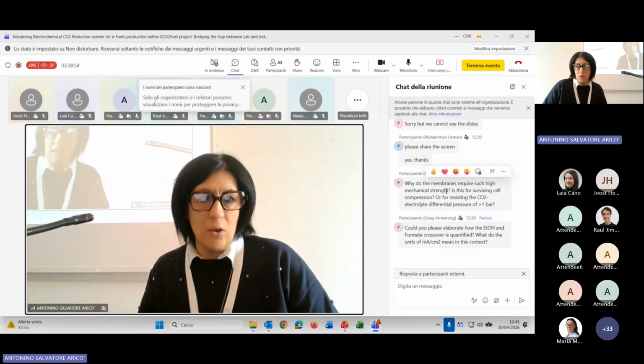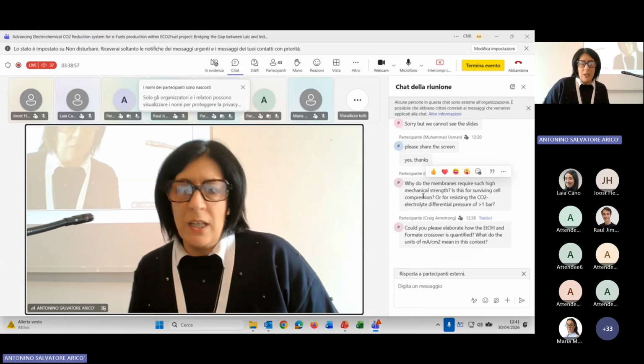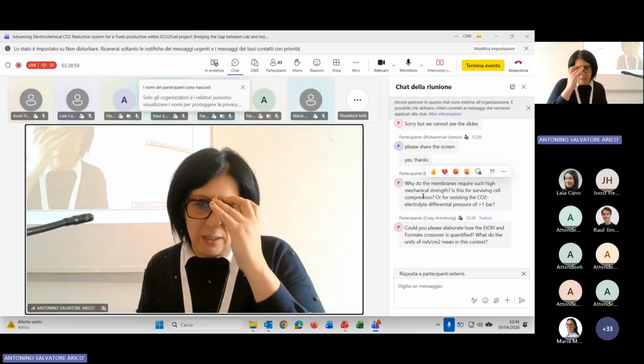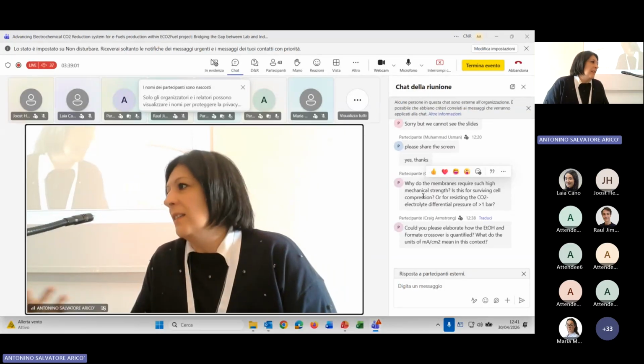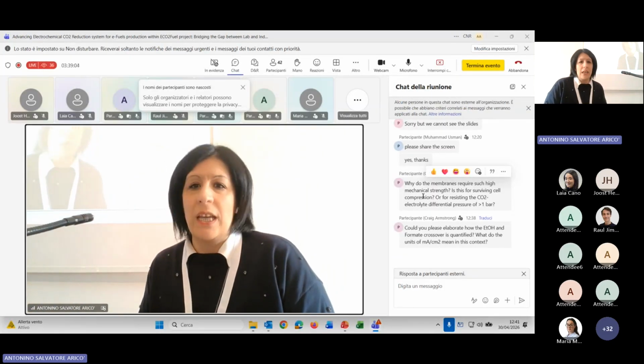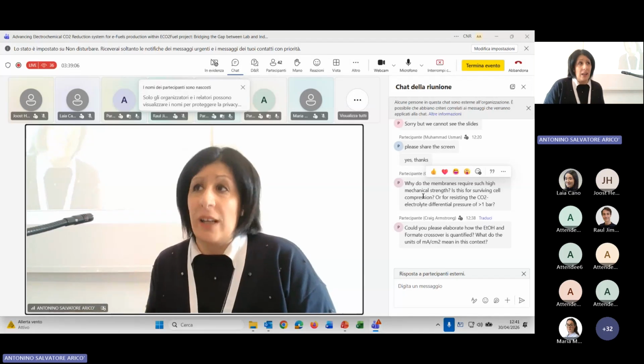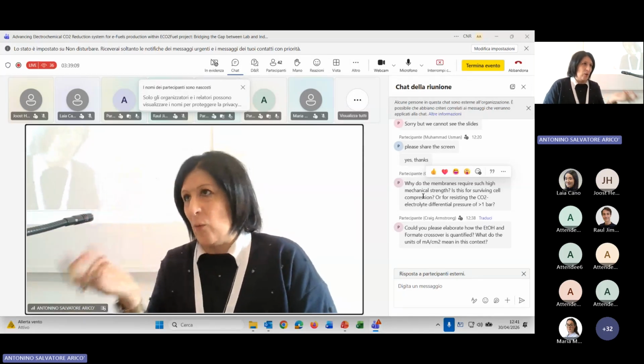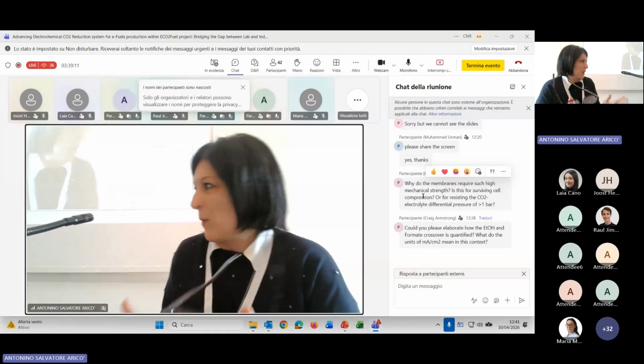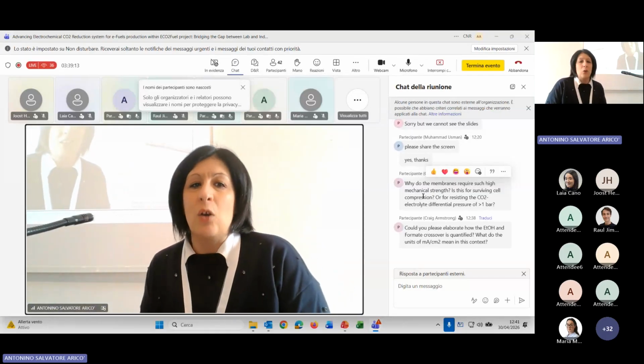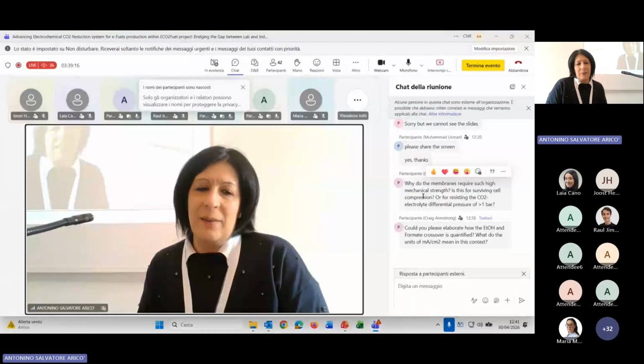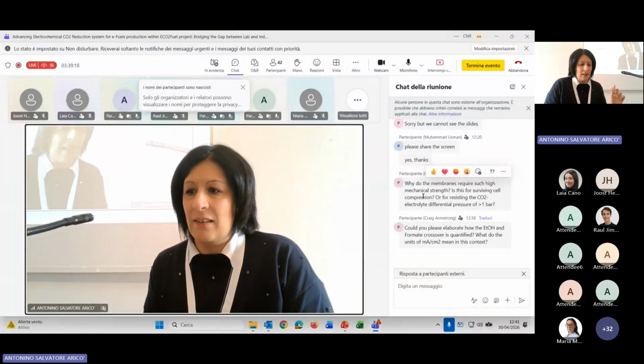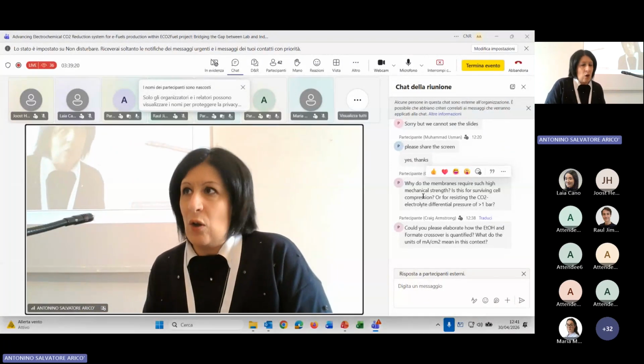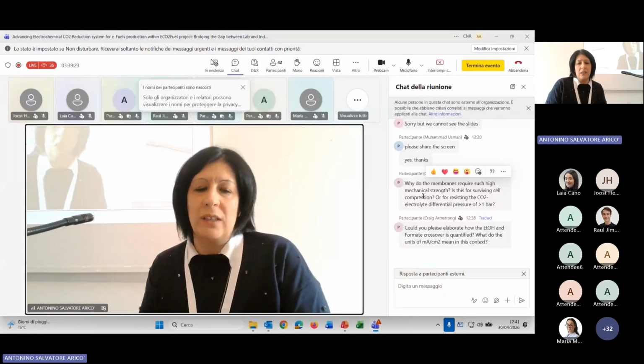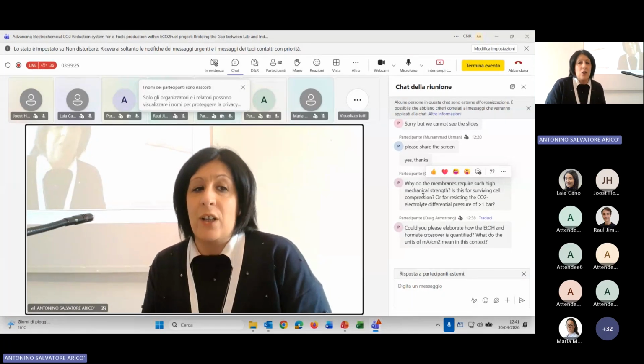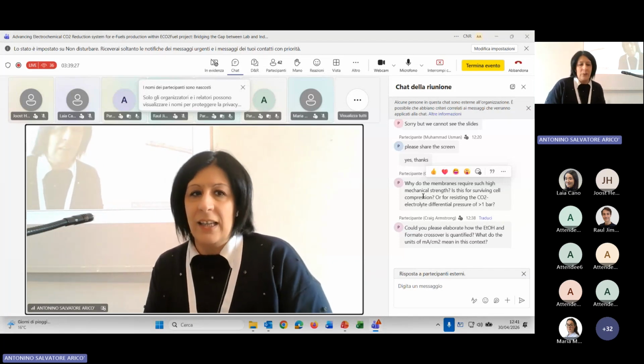Okay, this is a target of the project, but obviously it should resist the compression. In fact, in the first test of the stack, we suffered some broadening of the membrane, in particular in the framework. That is the typical broadening of a membrane when you assemble a zero gap cell. So to increase the mechanical strength during the assembly, and also obviously to sustain a differential pressure that can be present